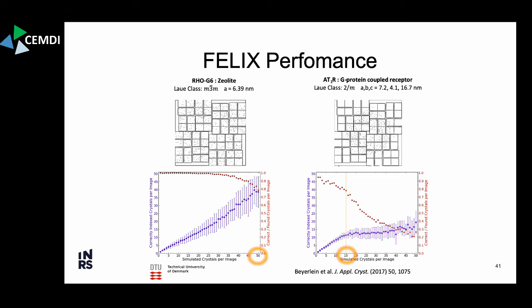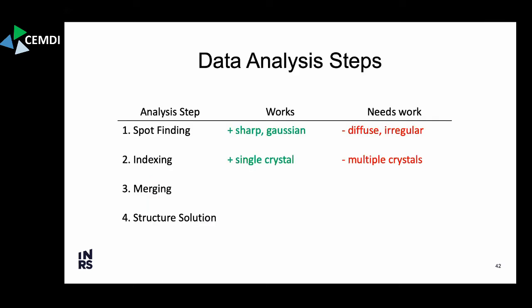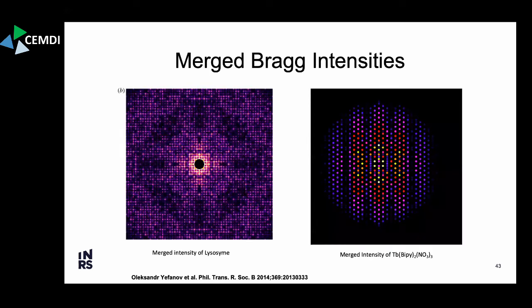So what we can say is that for some crystal classes, when the crystal symmetry is high, it works quite well. We're able to index even up to, say, pretty close to 50 to pretty good accuracy. And this degrades whenever the crystal symmetry decreases. So when we have lower symmetry, this algorithm doesn't work as well. And then maybe you say, well, your cutoff is more like 15 to some reasonable accuracy. So this still needs some work. That's just one approach, and it works for pure mixtures of polycrystalline materials, but it doesn't work well when you also have polymorphic, so multiple different crystal classes all mixed together.